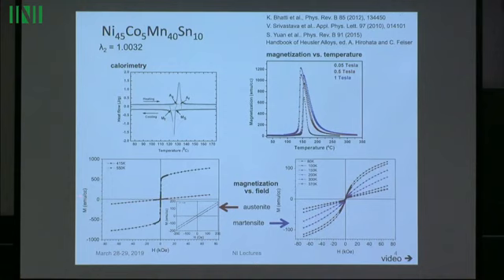So in fact, even with a very small applied field, we get quite a good fraction of the total magnetization. It's also shown up here. With 0.05 Tesla, that's a very small field, we're already up here. At 0.5 Tesla, we're up here somewhere, and at 1 Tesla, we're up there. That measurement is done under an applied field.